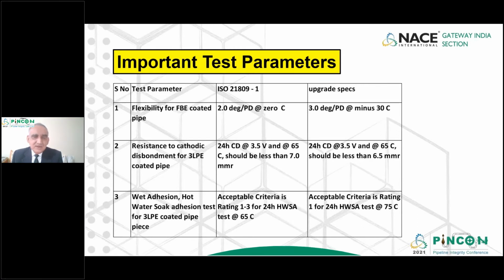And normally the ISO standard is referred to in most of the specifications, but in this case, ISO is a very easy specification to meet, 2 degrees per pipe diameter at 0 degrees Celsius. There is a need to have a more stringent specification so that there is assurance that this will not have any probability to crack or fail when the pipeline is constructed. So our suggestion has been with several companies, and some of them have adopted 3 degrees per pipe diameter, tested at minus 30 degrees Celsius. And this is coming from a CSA specification. So there is already a regulatory spec available, and many companies have adopted it.